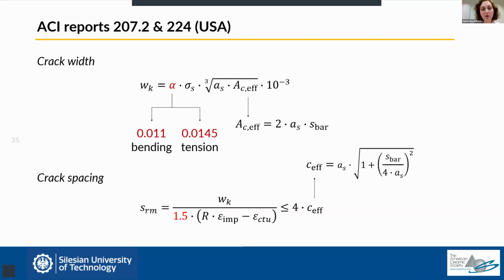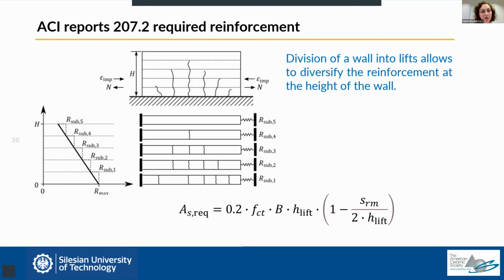Another difference is that the American approach allows us to check in which cracking stage we are with our loads, because we compare the crack spacing calculated this way with the crack spacing expected at the stabilized crack stage. Another very interesting aspect of the approach proposed in the ACI report is the way the required amount of reinforcement is calculated, which really allows for high optimization levels. Because I told you at the beginning of this lecture that the degree of restraint changes along the height of the wall. So normally in all of the previous approaches, we took into calculations the maximum value of degree of restraint. We calculated the expected crack width, and this allows us to calculate the required reinforcement.